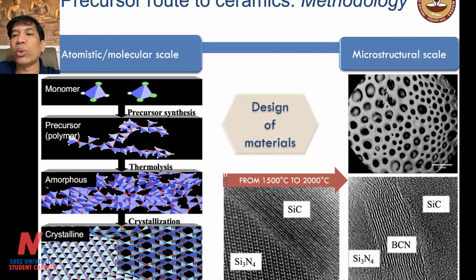For example, here you can see a microstructural engineering where you can find very nice pores which are meant for, say, photocatalytic applications. And at the same time, you can see the high-resolution transmission electron micrographs here, where we show how to control them and how to make them extremely high temperature resistant, say from 1500 degrees Celsius to 2000 degrees Celsius by just microstructural engineering.